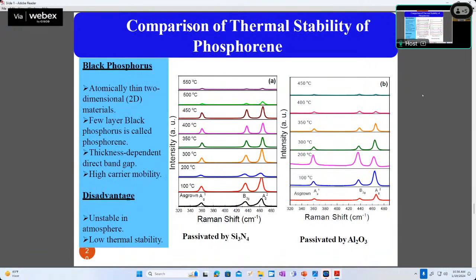The same thing is kept for comparison. We have seen that with silicon nitride passivation, this film is stable up to 550 degrees centigrade, and with aluminum oxide passivation, it is stable up to 450 degrees centigrade. So obviously the silicon nitride passivation is better for fabricating high temperature devices using black phosphorus.